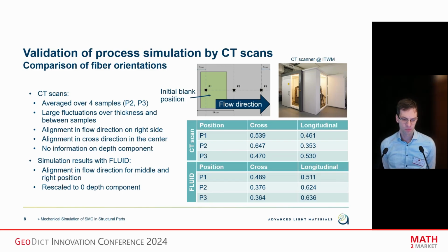And as you see from these numbers, for example, at P1, at the position where the initial blank was positioned, the agreement is quite good. At P2, the agreement is actually not very good in the center of the plate, but at the same time, the variations between the CT scans are also very large. And at the rightmost position, P3, we have a slight alignment of the fibers in flow direction, both in the CT scans and in the simulation. So this is far from being exact, but at least it gives us some validation of the process simulation results.